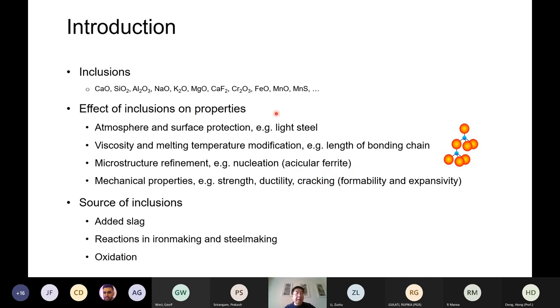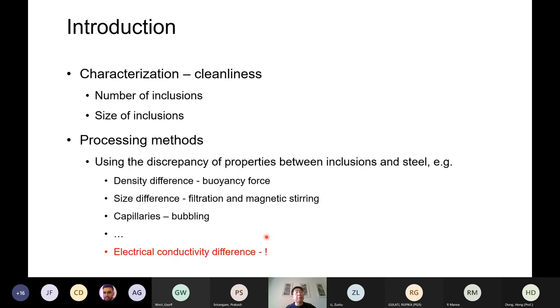So there are so many different effects which inclusions have. So we need to control those inclusions. The source of inclusions, as I said, a lot of them are added. We just choose to add them. And then some of them are formed during steel making from oxidation. And a lot of them are due to the chemical reactions in iron making and steel making, which form those inclusions. So how to represent inclusions? Many people just use the number of inclusions, or we say a fraction of the inclusions. And also the size of the inclusion is most important. We don't want the inclusions to be very large. So we need small inclusions.